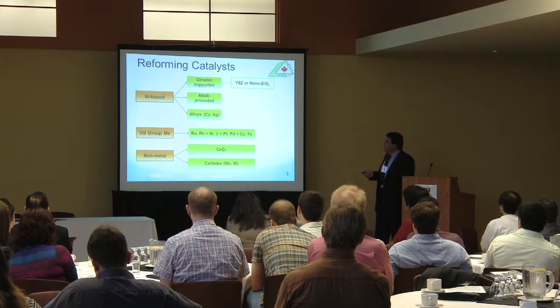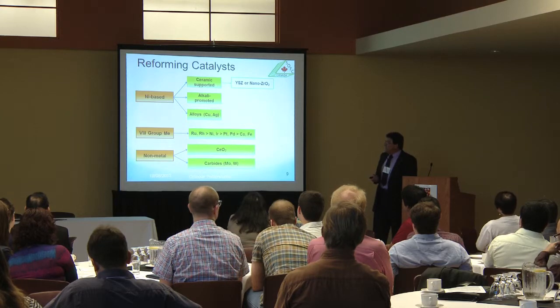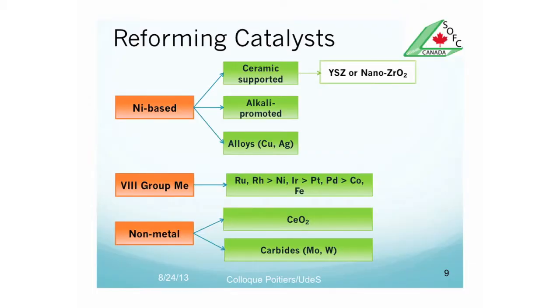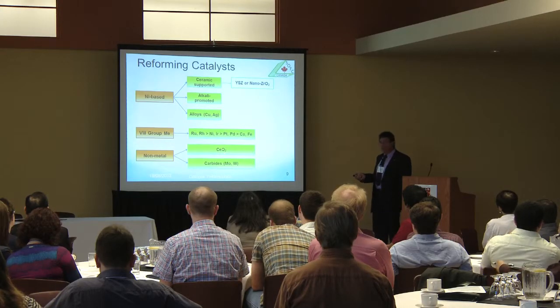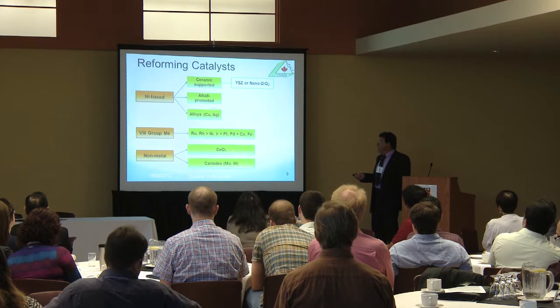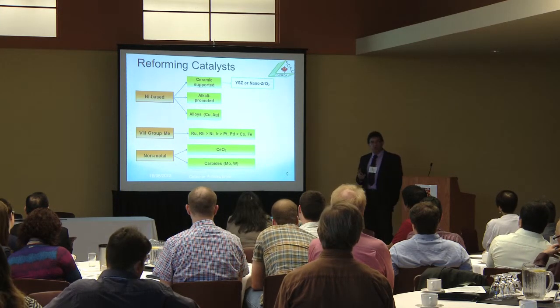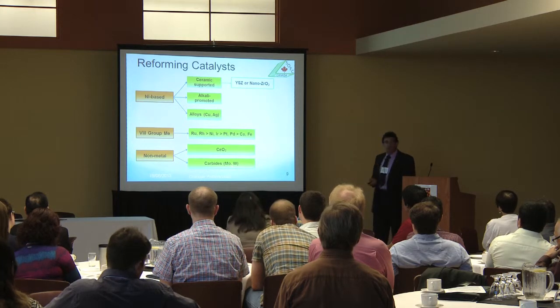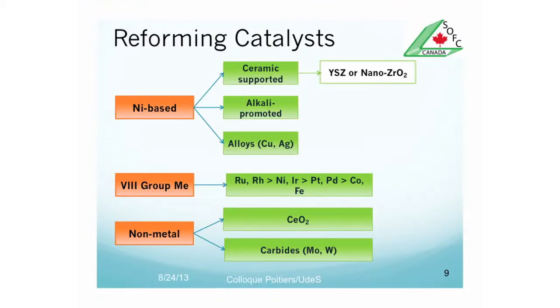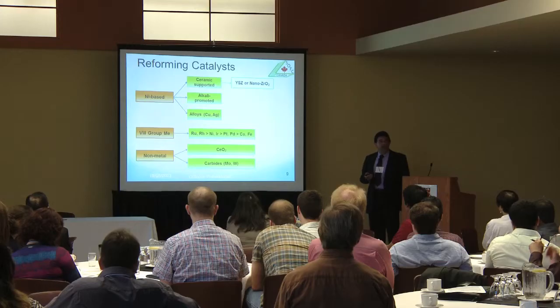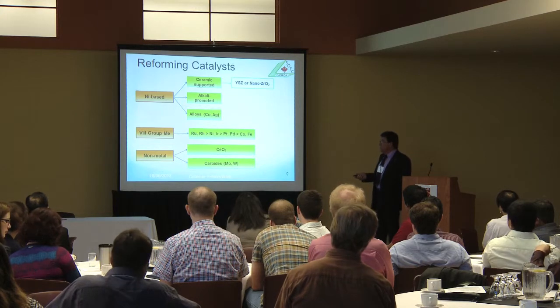The other metals which have been tried, with success, are the noble metals. Very expensive, and at the same time poisoning due to heteroatoms like sulfur is not hindered by this type of metal. And the non-metallic, that is ceria, can be used pure as a catalyst, but the activity is 2 orders of magnitude lower. And the carbides are very efficient but need high pressures. If we have no higher pressures, then the carbides lose their consistency and they break down.